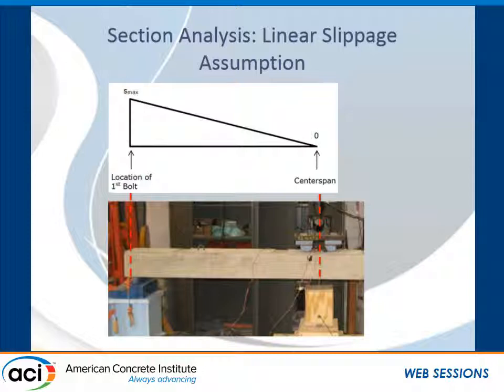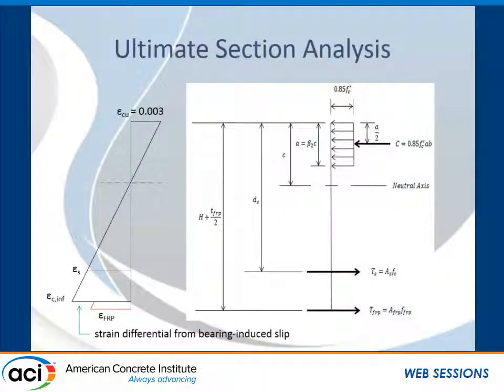Now, based on the assumption of the linear variation in slippage over the span of the beam, an ultimate section analysis is developed using an iterative procedure, and the nominal moment capacity and failure mode are calculated for cross-sections. We looked at rectangular compression zones. In the section analysis, we assume that concrete crushing occurs at a strain of 0.003, consistent with 318, and use the equivalent rectangular stress block to approximate stress distribution in concrete sections at failure.